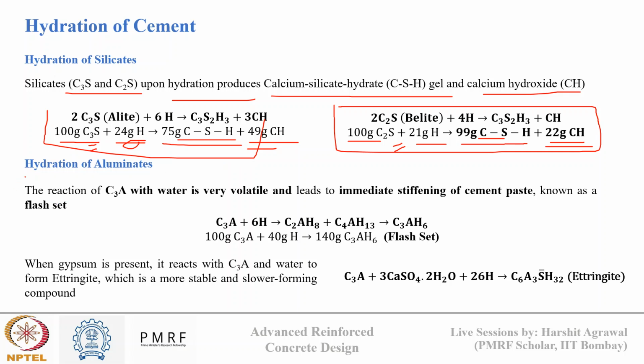Now, in case of aluminates, C3A is very reactive due to its structure. It has an open cubic structure, which makes C3A very reactive. So the reaction of C3A with water is very violent, and this leads to immediate stiffening of cement paste, which is known as flash setting. So if you see here, 100 grams of C3A combines with 40 grams of water to produce 140 grams of calcium aluminate hydrate, which causes flash setting.